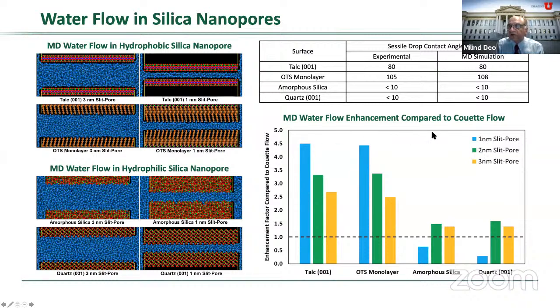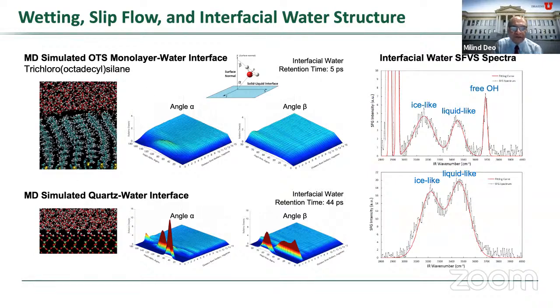And the molecular dynamic simulations of flow in these channels, now these are not tubes, but Couette flow in these, shows, again, very small enhancements in the hydrophobic systems and more or less no enhancement or reduction in this is for water, in the hydrophilic system. And this paper has been published in Colloids and Interfaces. Again, more evidence to see how the organization of these fluids at the surface affects.